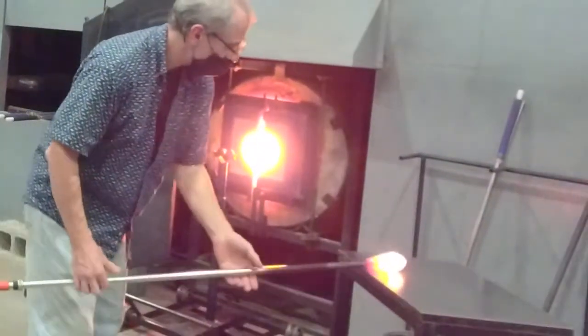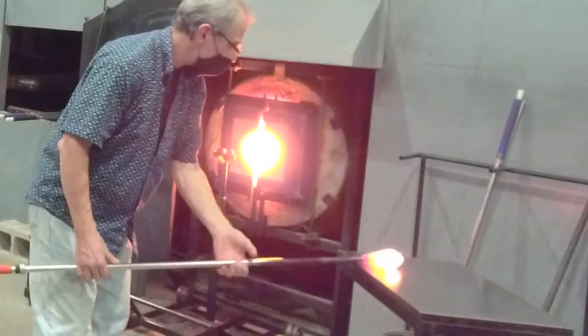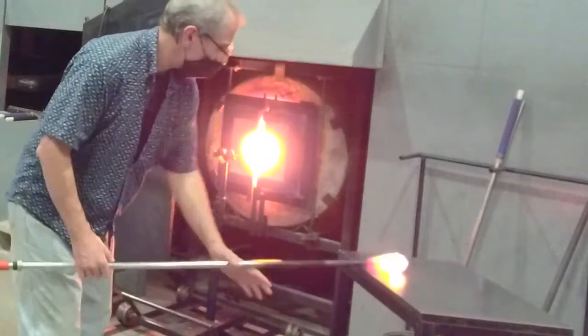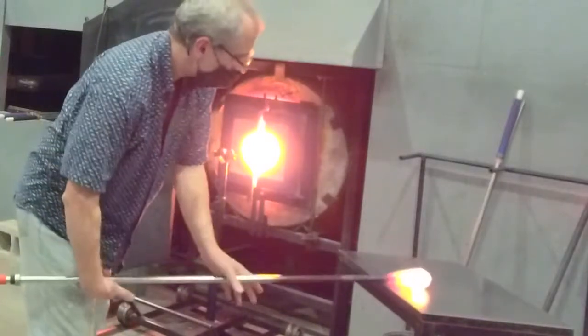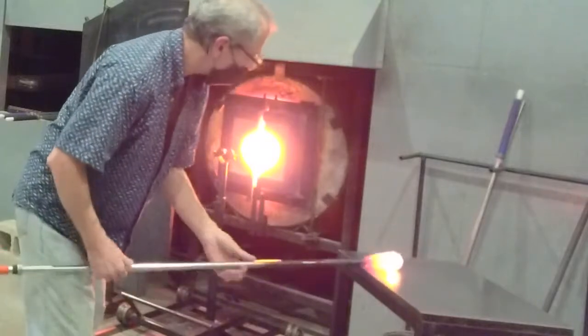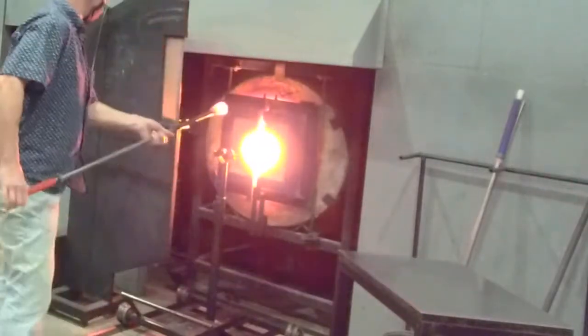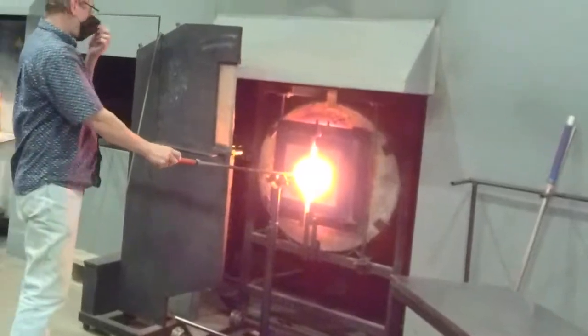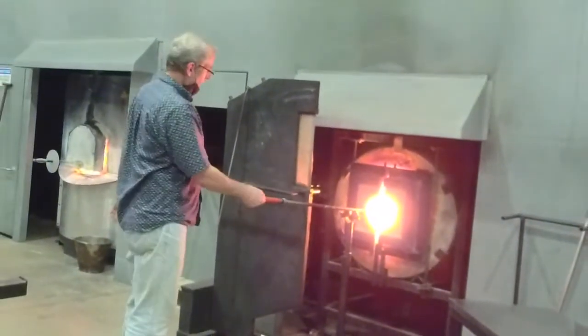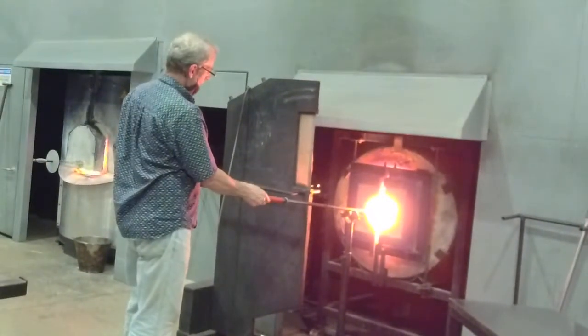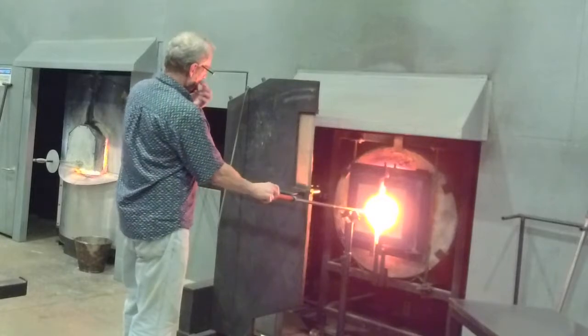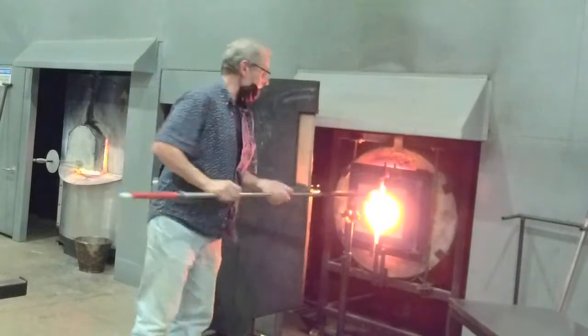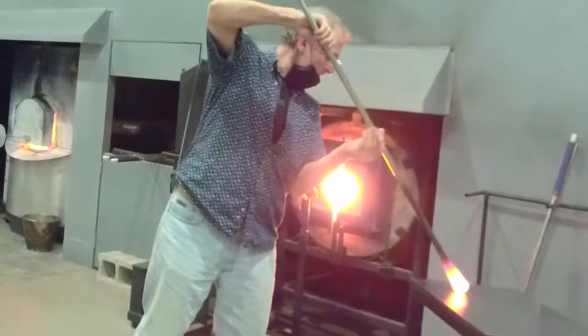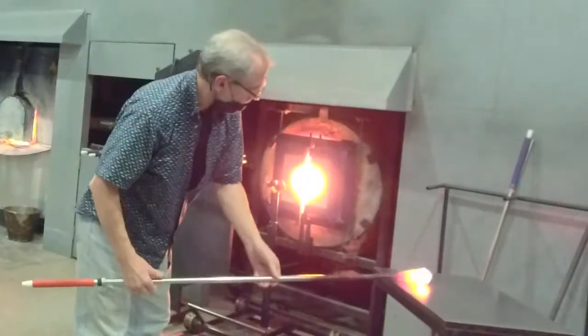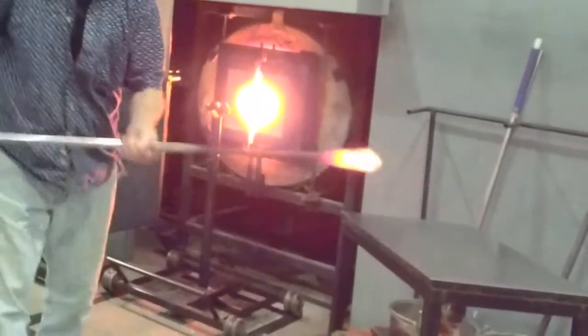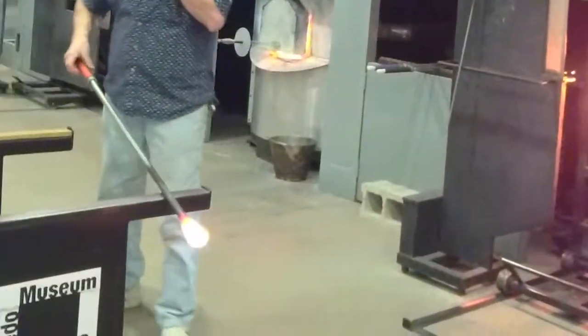Now this fresh layer of molten glass is the hottest part of this gather. While the inside, the bubble, looks very hot, it's actually several hundred degrees cooler than the outside. So the reason why he wants to reheat the glass is so that all of the glass inside the bubble and the outside is the exact same temperature. We call this homogenization, where all the material is the same temperature. All the particles are lining up together.